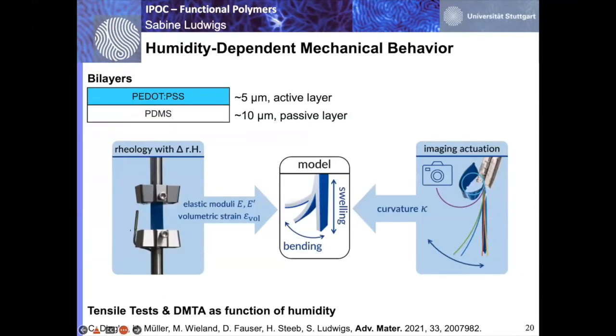And one step going further, in this particular experiment, the passive layer was 10 micron, PDMS, as I said, 5 micrometer. So the idea was really we use defined rheology as function of the relative humidity. So we make these films, which we use for the actuators, also for rheological measurements. And from the rheology experiments, which are based on tensile tests and also DMTA measurements, we get out the elastic moduli, but also volumetric strains. We put this then into a model.